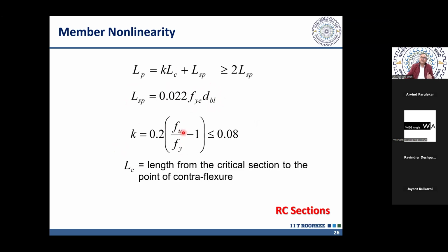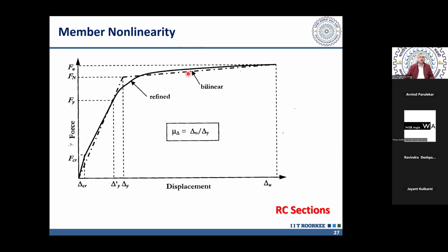Because larger the strain hardening in the steel, longer length of the steel will yield and longer plastic hinge length we are going to get. And longer is the plastic hinge or larger is the plastic hinge length, more ductility, more energy dissipation we are going to get. So that's why this ratio Fu by Fy is important. And if you look at IS 13920, IS 13920 also fixes a minimum value of this. I do not remember whether that is 1.15 or 1.2. So a minimum value of Fu over Fy is given in our code. And that is to ensure that the plastic hinge length should be sufficient, because this length will decide how much energy we are going to dissipate.